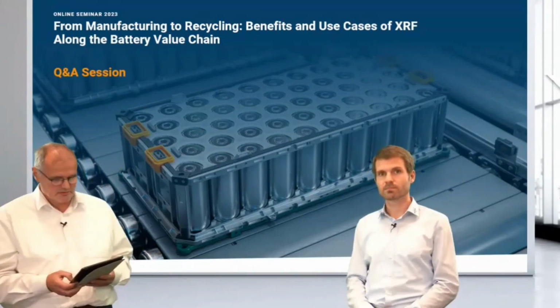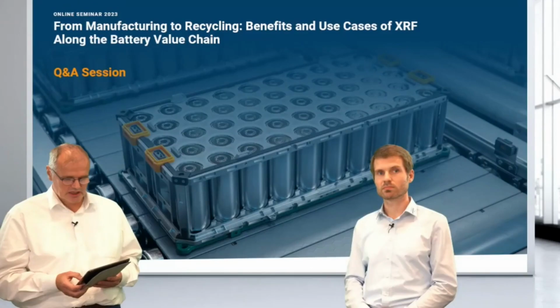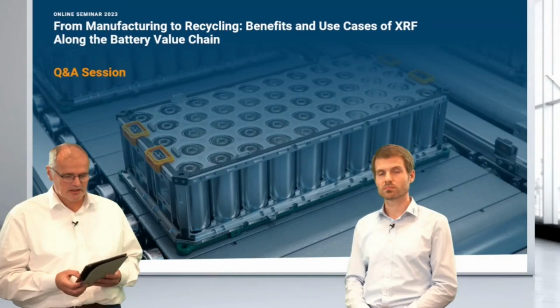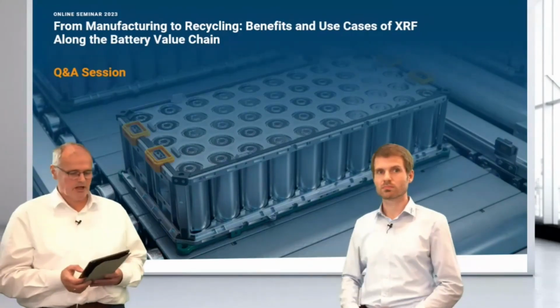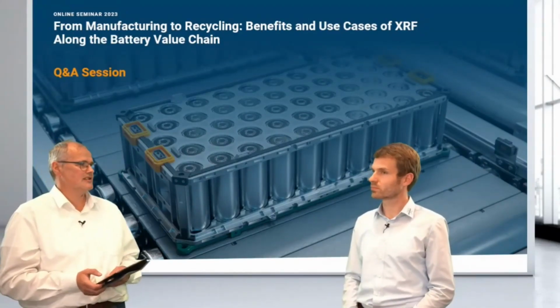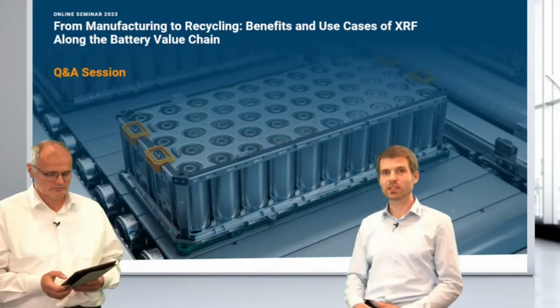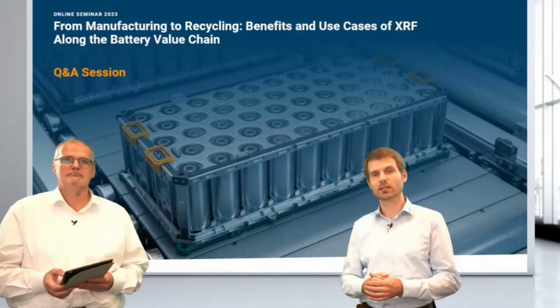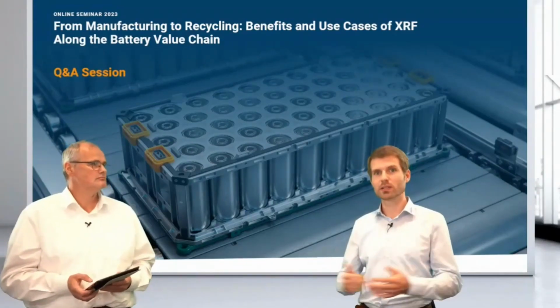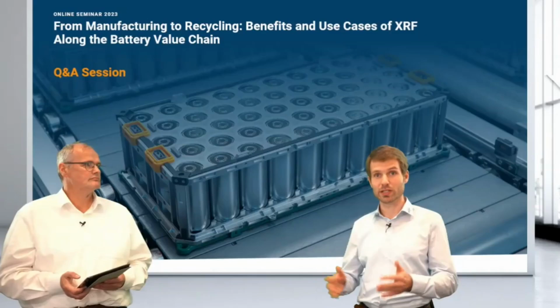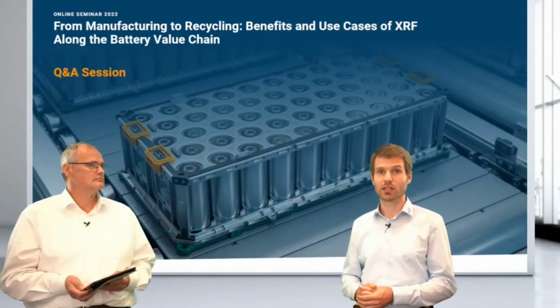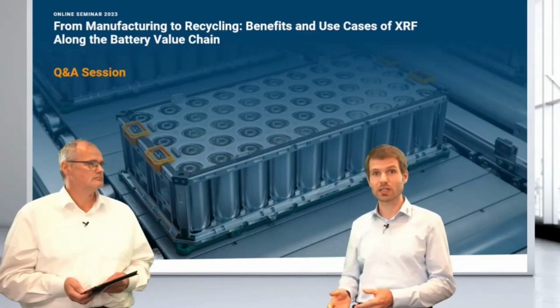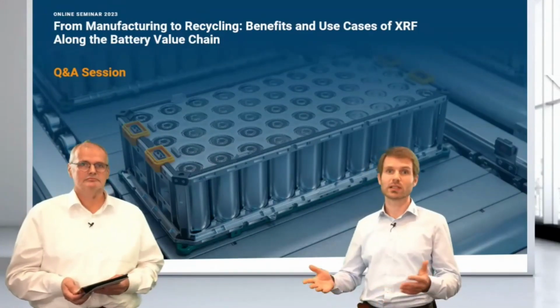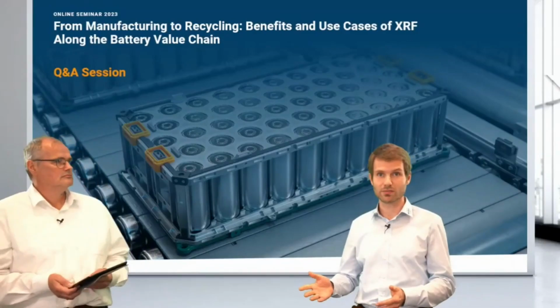So let me quickly check that we have covered every question. The quantity of sample amount required, could you make a statement there, Adrian? Yeah. As you've seen maybe in the part Hannes has shown, a typical material amount is in the gram range, so 5 to 10 grams of sample or milliliters that you put in a liquid cup, or if you press a pellet, we typically use like 8 to 10, 15 grams